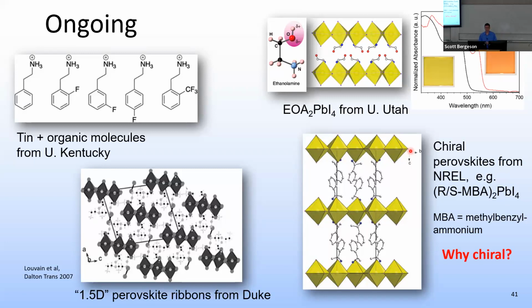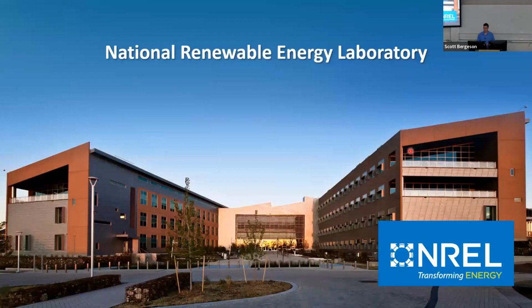And chiral is interesting because chirality can be related to things like circularly polarized light. So you could get a detector that detects circularly polarized light that's right-handed better than it detects left-handed circularly polarized light, or sources of photons that produce circularly polarized photons of one helicity or the other. So some cool things there.